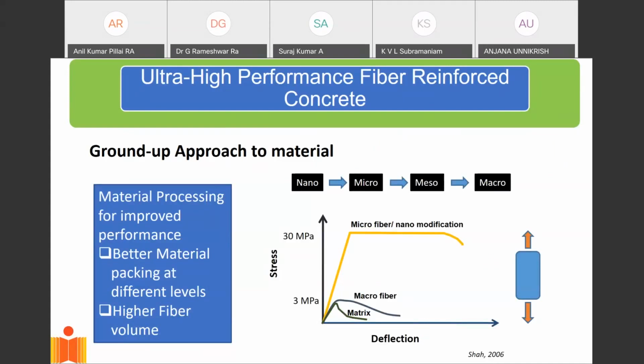And this is done by packing of the material. We pack the material by carefully paying attention to the different scales, packing at the nano, at the micro, and the meso scale. We introduce a very high fiber volume into the material, and the high fiber volume is introduced through processing. And I'll talk about processing in the next few slides. By doing so, we are able to produce this UHPC, ultra high performance concrete, which gives us very high tensile strengths of about 30 megapascal, and a very ductile response. Basically, it cracks, but it does not fail.